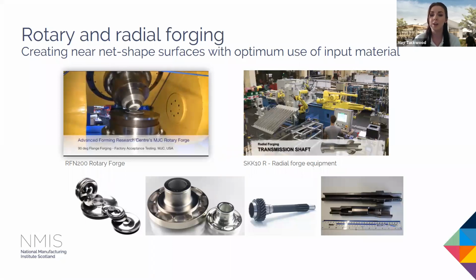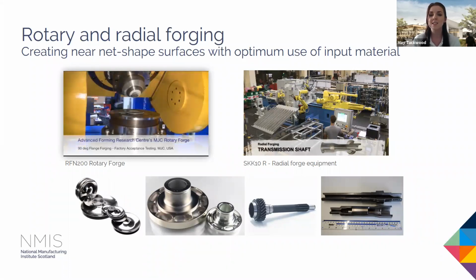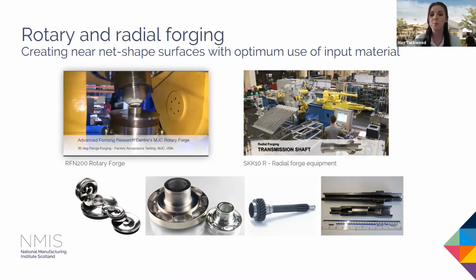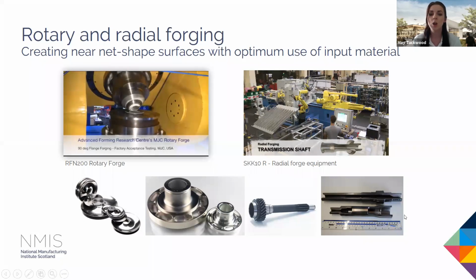Now, the key advantage of radial forging, particularly compared to flow forming or some of our other cylindrical forming processes, is the ability to create internal features. So flow forming and shear forming are limited on that internal diameter being constant. The part is forming against the mandrel at all times. And while the same is true for radial forging, the mechanism of the process lends itself well to internal steps. So you can see in some of the examples there, and also internal splines, which is particularly advantageous for transmission shafts.